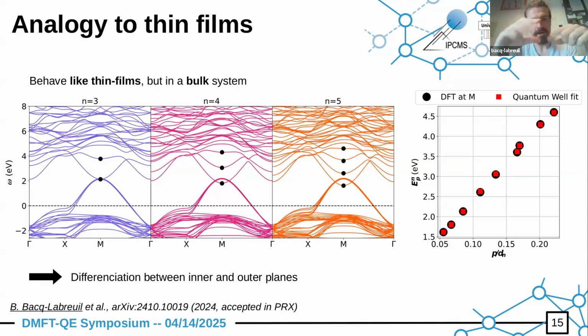And these conduction states offer extra hybridization for the inner planes more efficiently than for the outer planes. This is similar to a surface type of physics, right? If you have a plane at the surface, only one side of the plane sees the rest of the system, while if you have a plane in between, it has both sides. It can hybridize to both sides. So this is what's happening, and what's promoting a little less correlation in the inner planes.